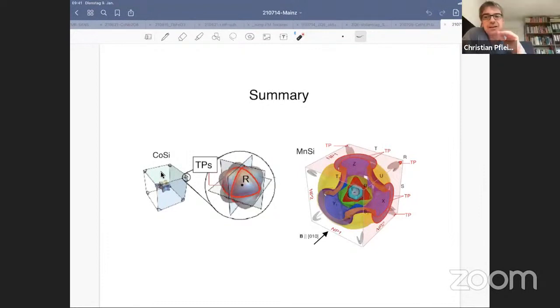I know that there's a history of debate between which is better, ARPES and quantum oscillations, and I don't want to get into this territory. But then I also mentioned the sample quality in terms of studies that were published by these Chinese colleagues. And they saw a little broadening, an asymmetry in their Fourier transforms, right? And we have samples which also show the same thing, but they're lower quality in terms of the resistance ratio, right? So in terms of preparing these materials, it is all right, but it's usually the way you can do quantum oscillations on materials that love to grow by themselves. And that's the case here, right? And if they don't like to grow, right, it's difficult.